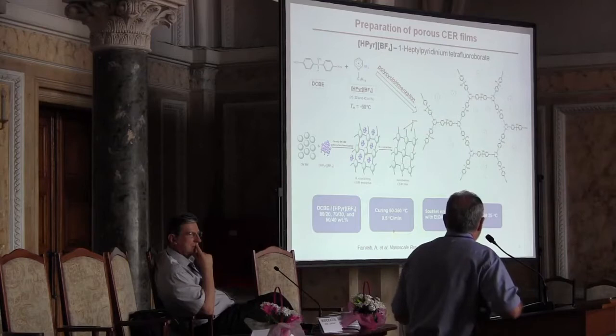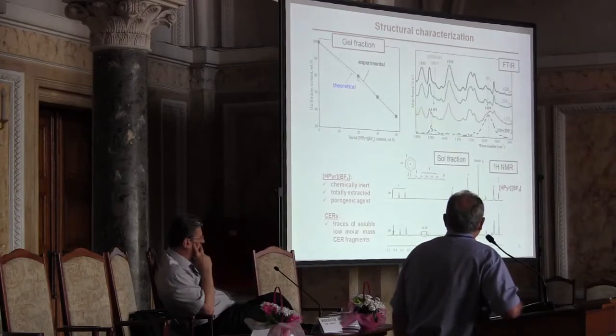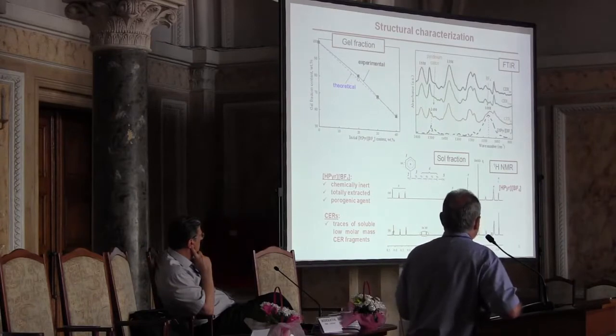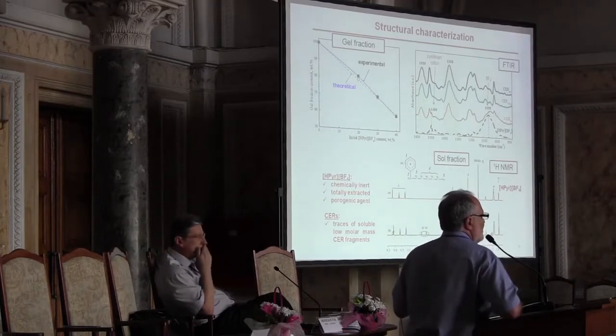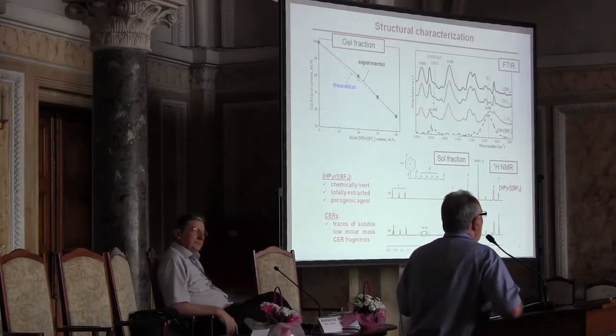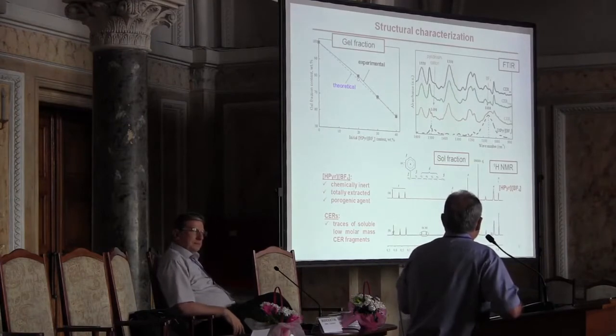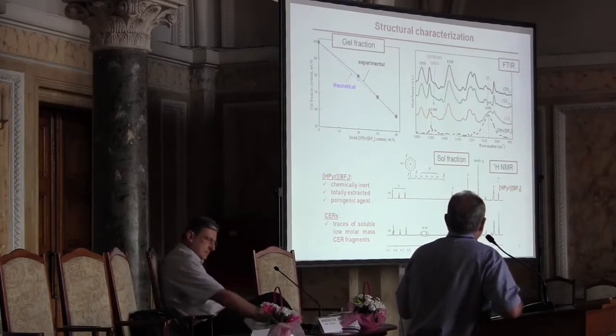It was a high temperature synthesis, and the composition was 80-20, 70-30, 60-40 with ionic liquid. Then the structural characterization. For gel fraction content, the theoretical and experimental values were very close. It means that there is no chemical interaction between ionic liquid and monomer or polymer synthesized, and this ionic liquid can be completely removed from the network after this synthesis.